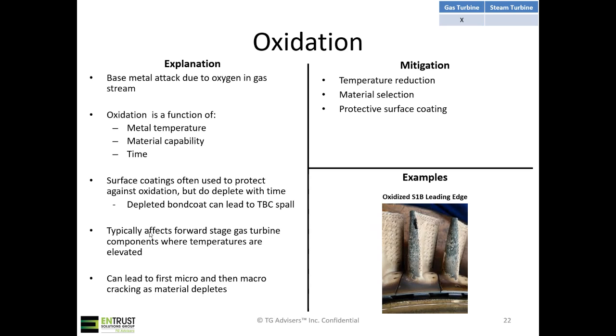It typically affects the forward stages in a gas turbine more than the aft stages, and obviously that's because your temperatures are hottest closest to the combustor. A lot of times it can lead to micro cracking and then to macro cracking or breached cavities if there are coolant circuits internal to the blades. So it's something that's very serious. The best way to protect against this is really temperature reduction, material selection, as well as applying a protective surface coating when necessary. There are multiple different types of coatings out there that will help protect against oxidation.